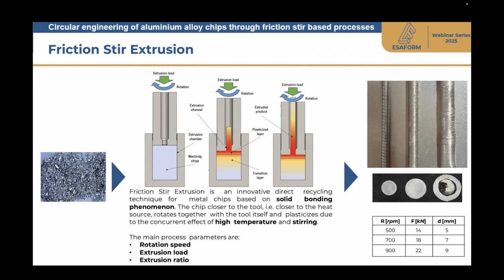Since, as we remember, the extrusion ratio definitely determines the mean stress in the middle of the wire in this case, but we would say in the middle of the extruded parts. And so in this way, it is very important in order to get proper and effective bonding conditions all along the product section, all along the wire section.